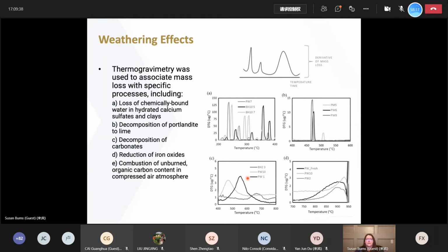So what we have done is we've used TGA analysis to come in and study the mass loss as a function of temperature in the ashes that we're dealing with. So what you see here are the TGA results, where we, first of all, burned off the chemically bound water in the hydrated calcium sulfates and the clays that were present in these ponded ashes. We can come in then and we can do a temperature increase. And what you see here, these sharp spikes are evidence of the decomposition of portlandite into lime. And then you can see as we go further with increasing temperatures as well, that we get decomposition of our carbonates with these relatively spread peaks, and we get reduction of iron oxides at higher temperature.